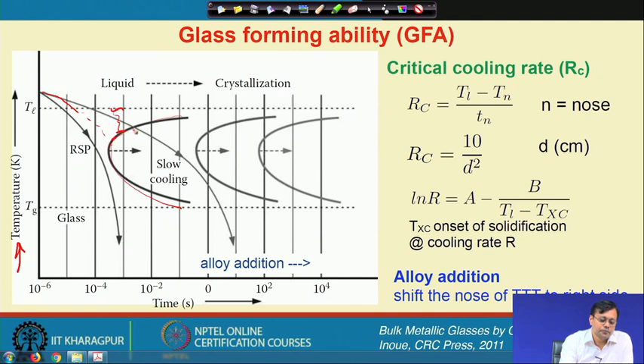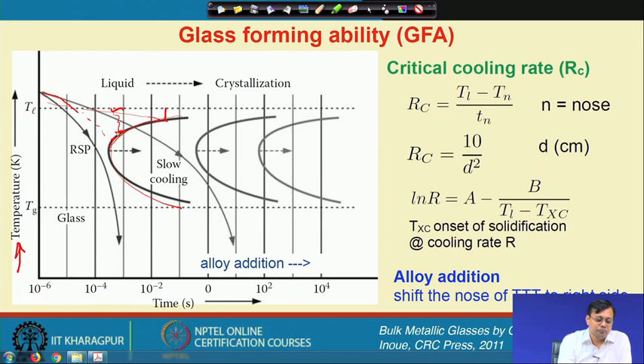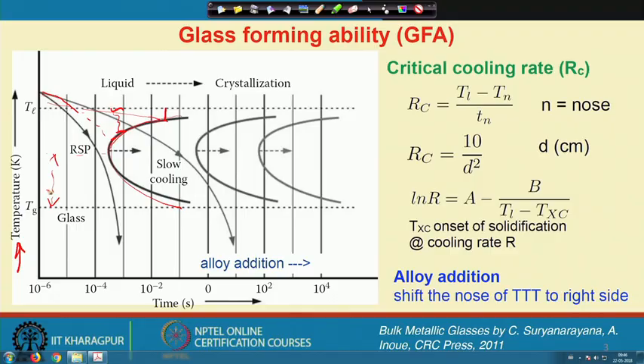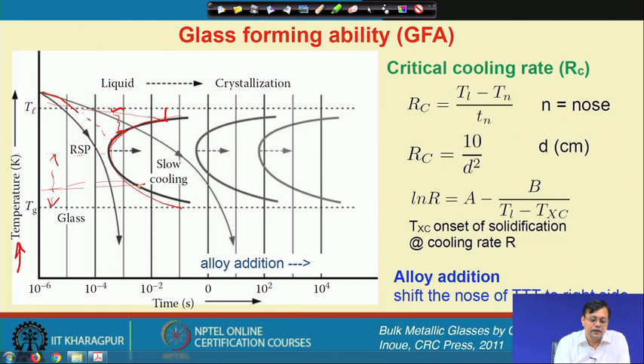Lower undercooling will give a larger incubation period for nucleation, whereas larger undercooling will give more nucleation in the melt. Below a certain temperature — usually the nose of the TTT — diffusion becomes sluggish. Since atoms need to form a cluster to make a nucleus, nucleation rate decreases. Diffusion in the melt also decreases, so we again get a larger incubation time. This explains why the shape is like a C.